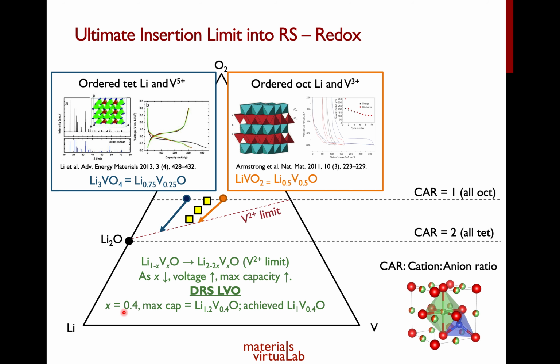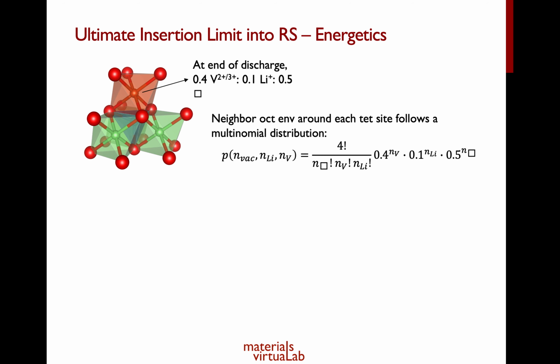We are operating at x equals 0.4, okay? And our maximum capacity is Li 1.2 V 0.4 O, and we have already achieved close to the maximum capacity based on this V2+ limit, Li 1.2 V 0.4 O. Experimentally, what Professor Ping Liu has achieved is Li 1 V 0.4 O, okay? So why can't we actually achieve Li 1.2 V 0.4 O? We do have some hypotheses as to the reasons why, and this is based on energetics, okay?